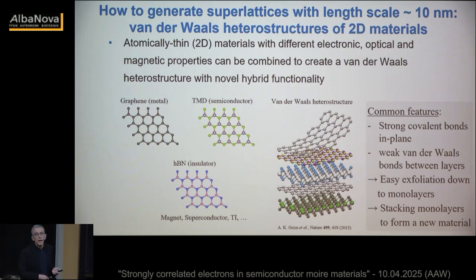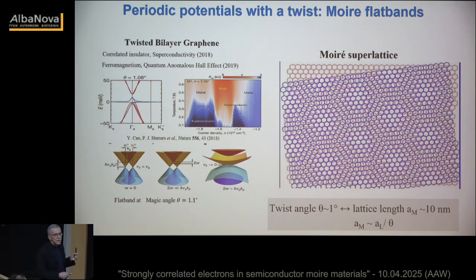Now, that's actually what the community has been dealing with for like 15 years. But what was realized by Allan MacDonald and Bistritzer about 14 years ago is that there is a lot more you can do if you stack two monolayers with a small twist angle. This is a picture of what happens. Two hexagonal or honeycomb lattices, it could be graphene or anything. When there is a twist angle, you see a new periodic structure appearing in the system. The period of this new superlattice is simply given by the underlying lattice constant divided by the twist angle. So if you have a twist angle on the order of 1 degree, you get a moiré period on the order of 10 nanometers.